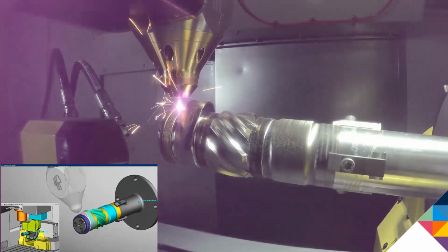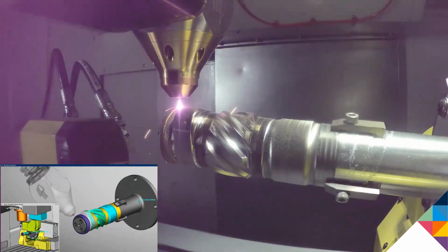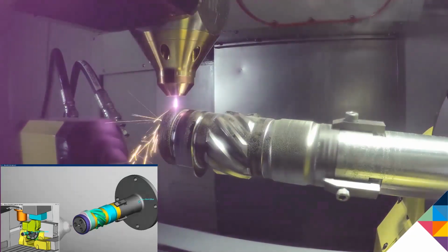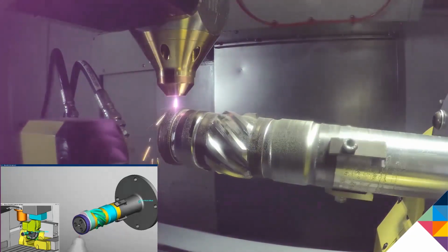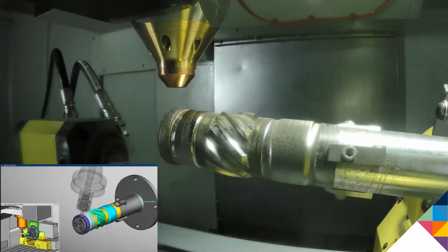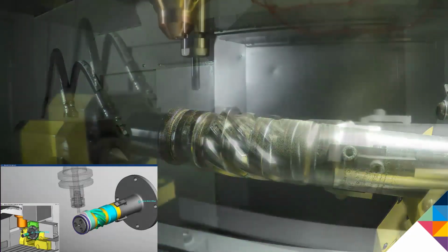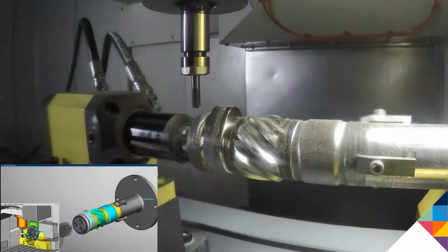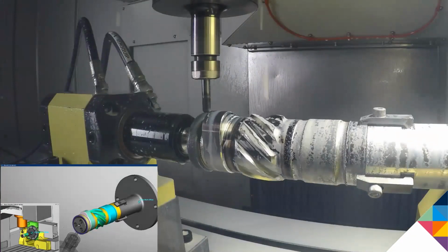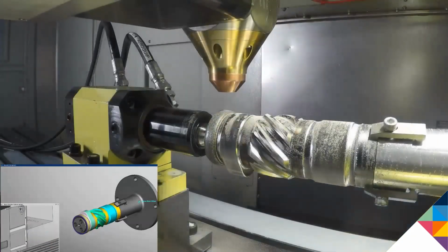You might also notice one small issue that we found with this. The first 3mm high build, when we come in with the milling cutter, it doesn't fully clean up. The cutter just barely scrapes the top of it. This taught us the importance of making sure we do a powder calibration before we run, because over the course of a few days, the flow rate seemed to drop a little bit.